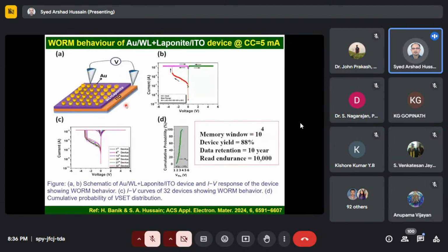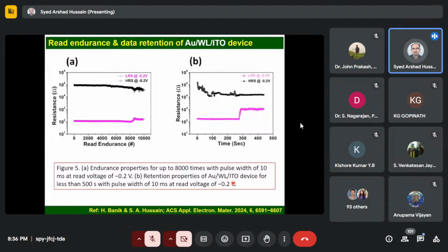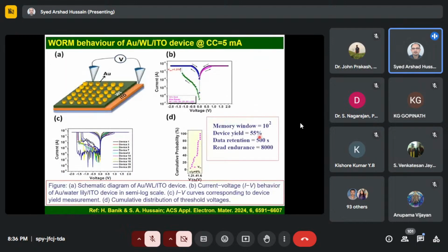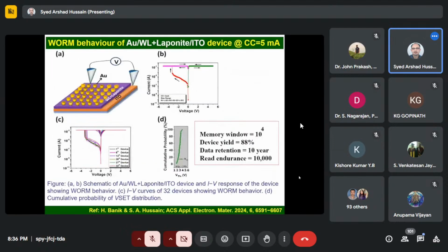Here we incorporated the clay laponite with the extract. And interestingly, you can see that the memory window increases several times. Earlier it was 10 to the power 2, but here it becomes 10 to the power 4. Device yield also increases from 55% to 88%. Data retention, it can retain the data even beyond 10 years. In the earlier case, it was only 500 seconds. Also it's possible to read the stored information more than 10,000 times.